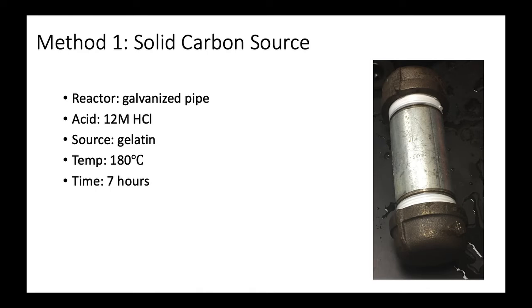I improvised a pipe reactor from a galvanized pipe nipple and 2 end caps, wrapping the threads in Teflon tape to improve the seal. My acid catalyst was 12 molar HCl, and I used gelatin stirred in water as the solid carbon source. I loaded up the reactor and heated it in a chemical oven at 180 degrees Celsius for about 7 hours. Some safety points I would like to highlight.